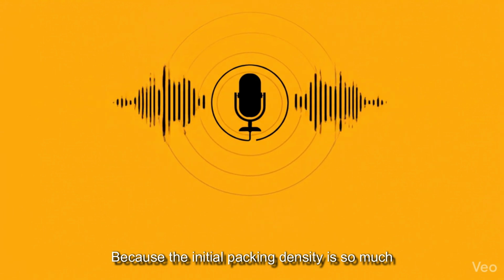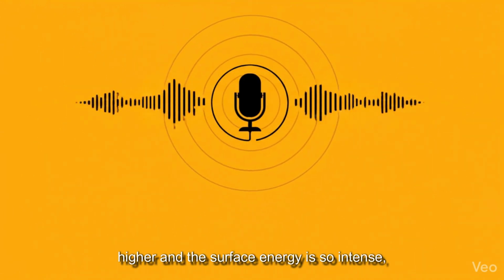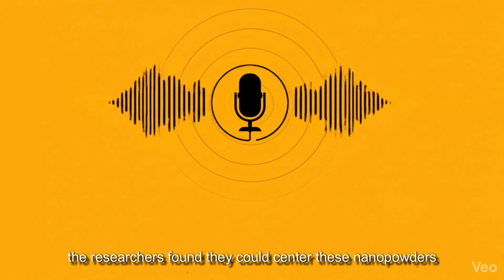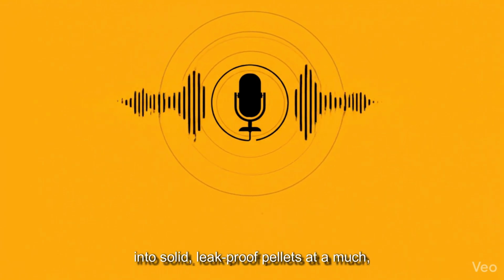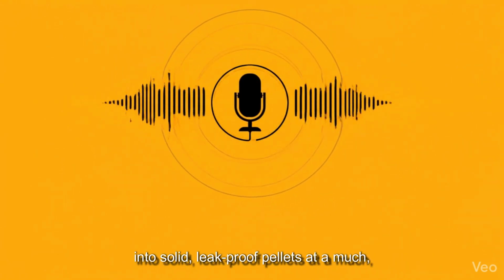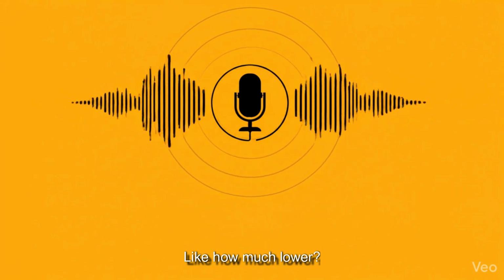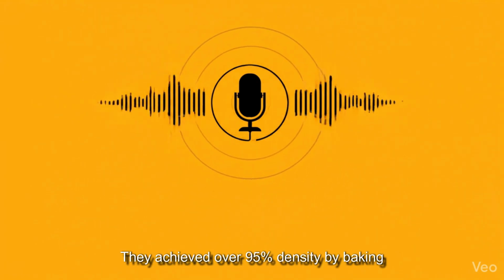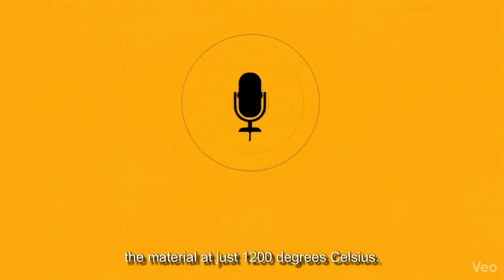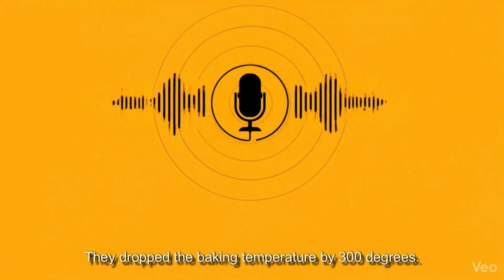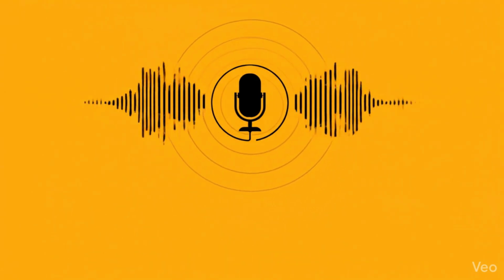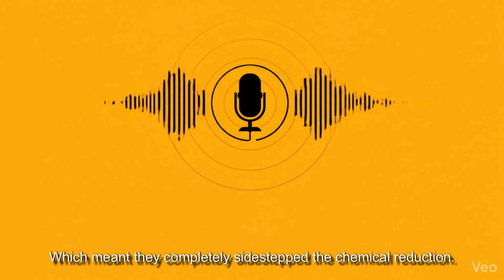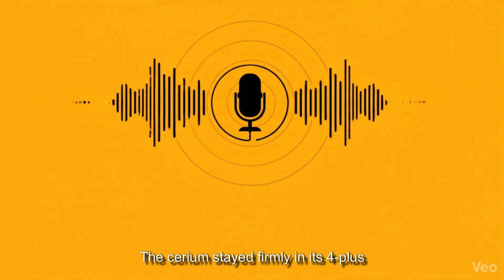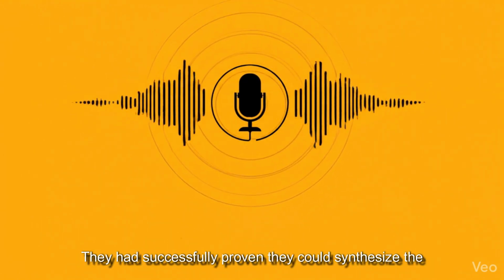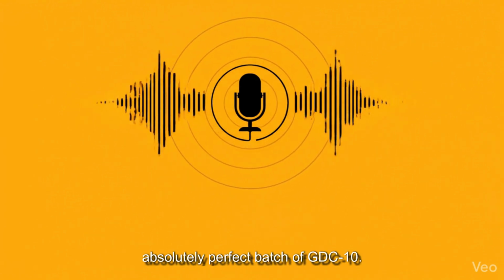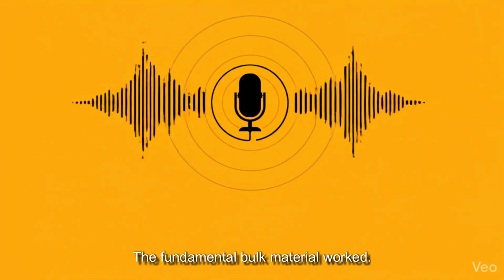Because the initial packing density is so much higher and the surface energy is so intense, the researchers found they could sinter these nanopowders into solid, leak-proof pellets at a much, much lower temperature. Like how much lower? They achieved over 95% density by baking the material at just 1200 degrees Celsius. They dropped the baking temperature by 300 degrees. Exactly, which meant they completely sidestepped the chemical reduction. The cerium stayed firmly in its 4+ state. They had successfully proven they could synthesize the absolutely perfect batch of GDC10. The fundamental bulk material worked.